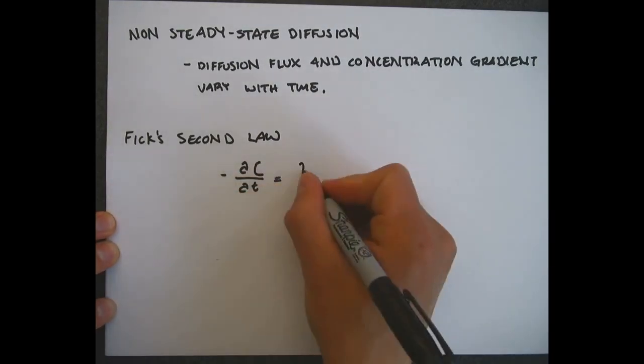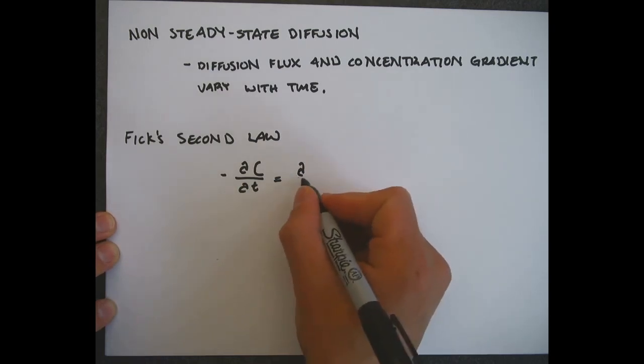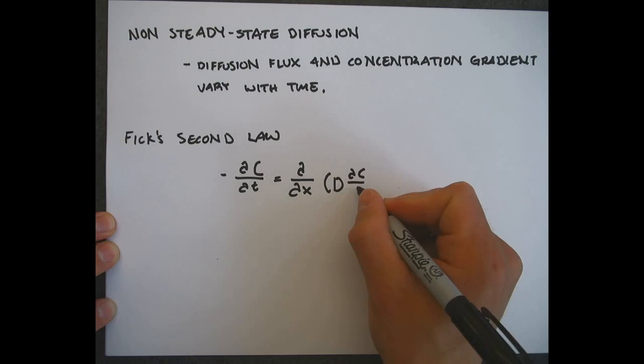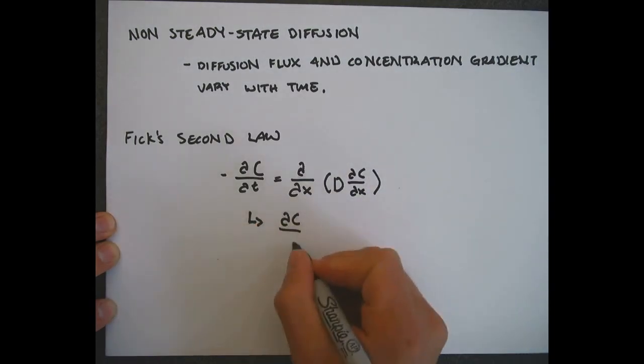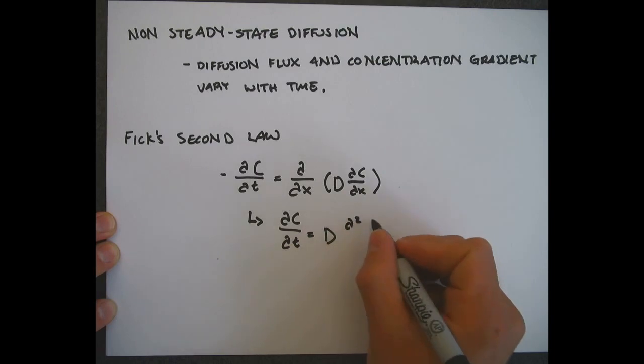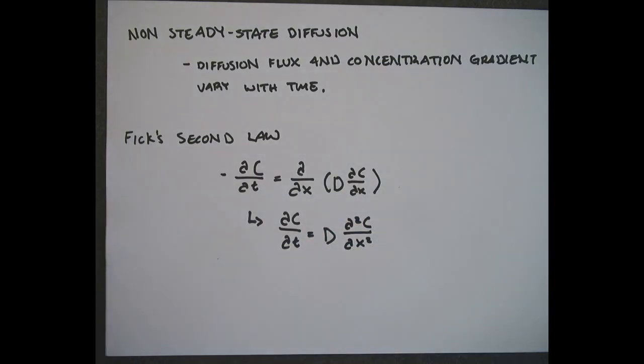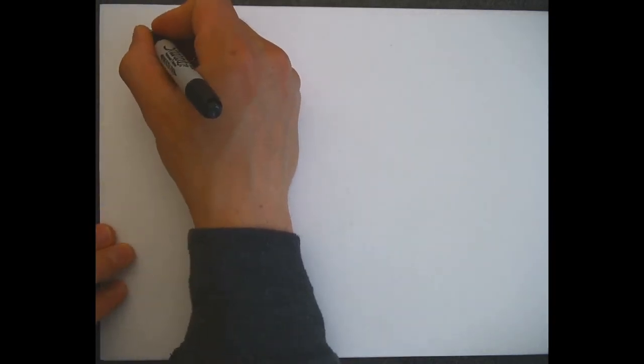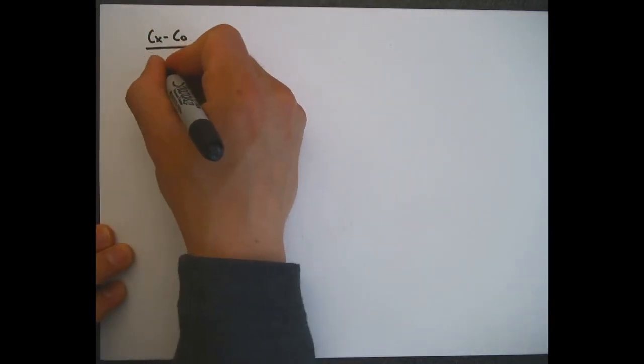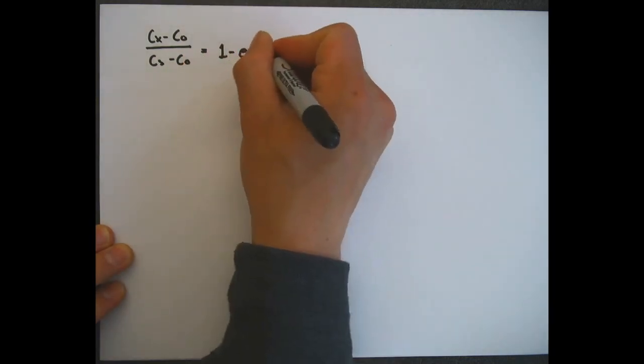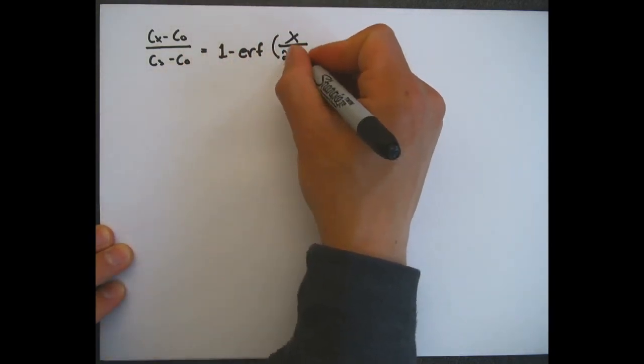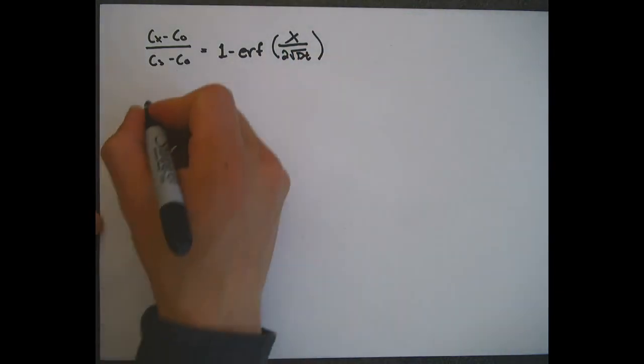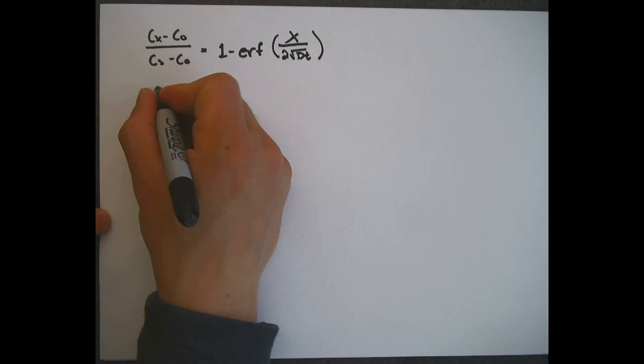So in order to find Fick's second law, what we do is we take the partial derivatives, and what we end up with is a partial derivative of the concentration over the partial derivative of time. And we set that equal to D, the diffusion coefficient, times the second partial derivative of concentration over the partial derivative of x, the position after a certain time, squared. Now, after giving the variables of Fick's second law some boundaries, what we end up getting is our error function formula, where C sub x minus C sub o over C sub s minus C sub o is equal to 1 minus the error function of x over 2 times the square root of Dt, where D is the diffusion coefficient, t is time, and x is a certain depth.